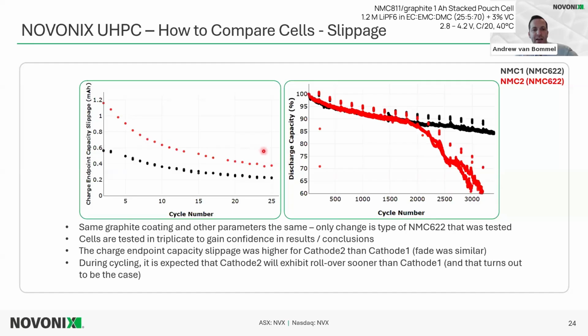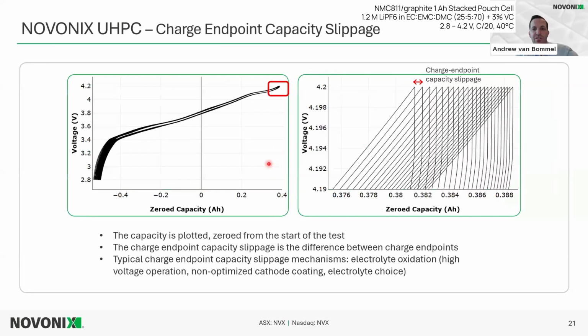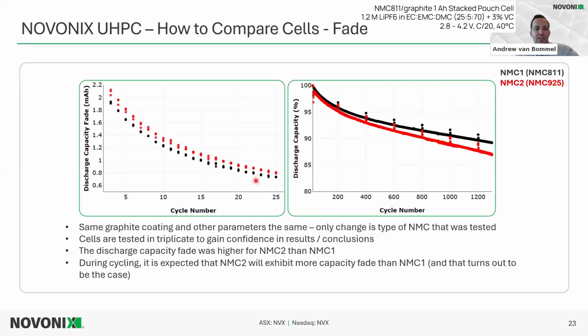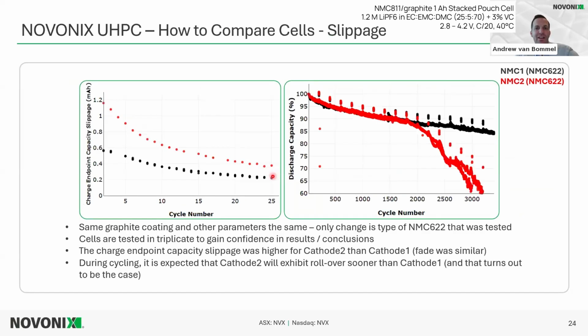So yeah, they're both leveling out, but we definitely look at the magnitude of the slippage, and I could reference the graph here. The charge endpoint capacity slippage is the difference between the end of one charge and the next. We look at the magnitude of this, because if that amount is larger, then that means there's more, for example, oxidative processes happening, maybe electrolyte oxidation, and that will result in that rollover. So we do compare the magnitude of one cell compared to the other. This is important. It's not only the trend. We would not normalize slippage here when it's shown as slippage per milliamp hour.